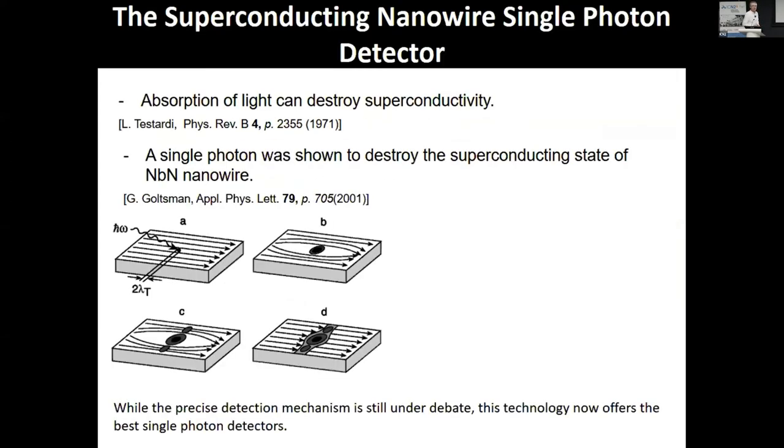And then I'll just tell you, to finish, about detectors. I already gave you some ideas. It's a Russian invention from 2001. And what they did at the time was something that really shook the world already, our Russian friends. They made a superconducting film of thickness of about 5 nanometers, with a width of about 100 nanometers. They made that device.